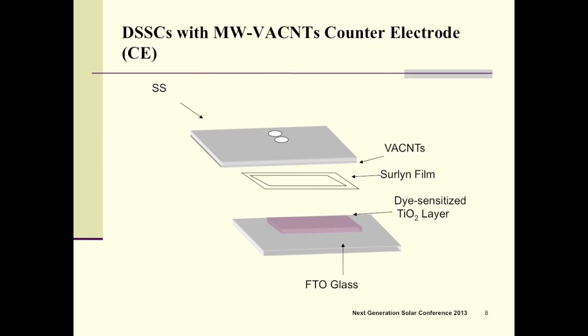Here is the structure of my cell. Below is the photoanode, and the upper one is our counter electrode having vertically aligned carbon nanotubes instead of platinum. And we use the Surlyn film as a separator, and through those holes we fill our electrolyte, and then we tested our cells.